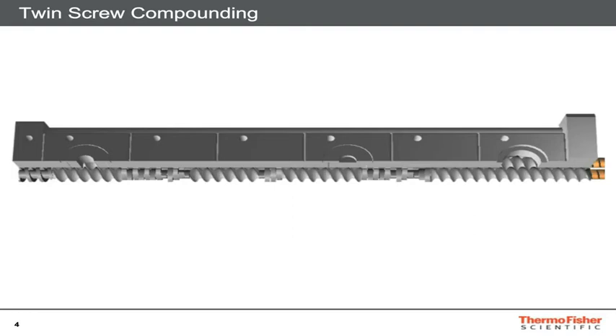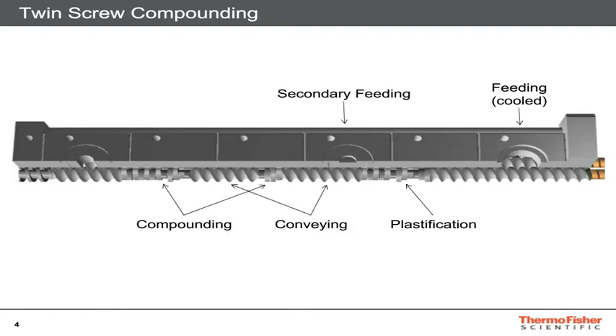So what is going to happen inside the extruder? We have here a cross-section of an extruder barrel with the different components and sections in it. The flow of the powder is from the right to the left. We have the feeding section where we infeed the polymer and/or the additives. Then the intermeshing co-rotating screws transport these into the first plastification zone. Then we have the opportunity to have a secondary feeding of our materials, a mixing zone, more conveying zones until the end where we're venting any volatiles out of the compounded material, and the extrusion section where we press the material through the orifice, producing the actual filament.